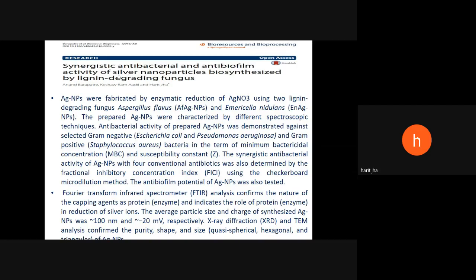Antibacterial activity of the prepared silver nanoparticles was demonstrated against E. coli, Pseudomonas aeruginosa, and S. aureus in terms of minimal bactericidal concentration and susceptibility constant. The synergistic antibacterial activity of silver nanoparticles with 4 conventional antibiotics was also determined by fractional inhibitory concentration index using the checkerboard microdilution method. The anti-biofilm potential of silver nanoparticles was also tested.